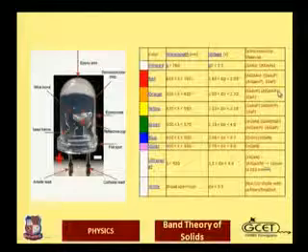The infrared LED, which is not a visible LED, has a wavelength greater than 760 nanometers, and the material used is GaAs or aluminium gallium arsenide. Gallium arsenide is the material which is widely used for the construction of these LEDs. A red LED can be constructed using GaAs, GaAsP (gallium arsenide phosphide), or GaP. The orange, which has a wavelength between 590 and 610 nanometers, can be constructed from GaAsP or GaP.